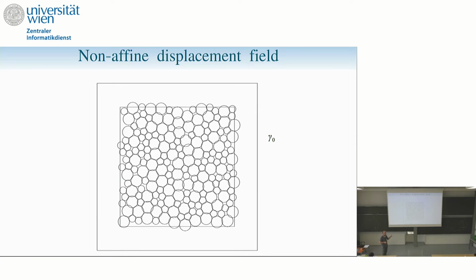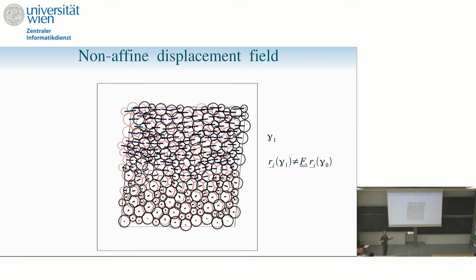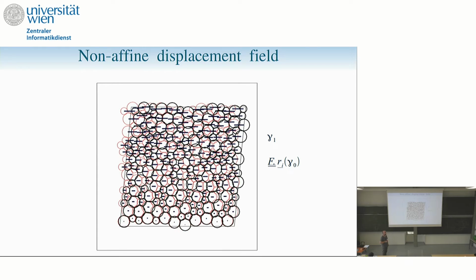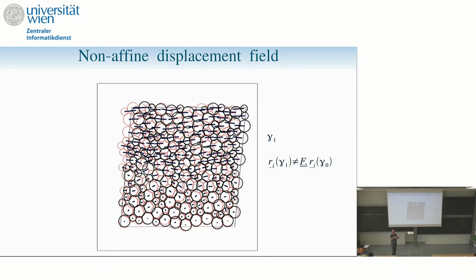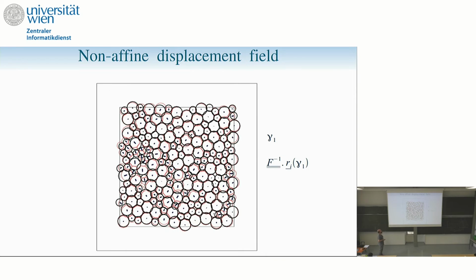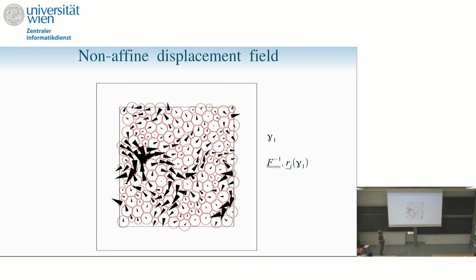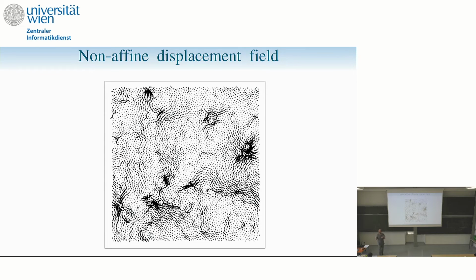Again, I start from a configuration. Here I shear affinely. I just bring the particles to the position specified by the macroscopic strain. That's it. There are periodic boundary conditions, yes. Now I minimize the energy. So I'm just decomposing the step I was showing you before: I strain affinely and then I minimize. Now I strain backward, and there is a residue. And this is a displacement field. If I take a larger system, I have this very large non-affine displacement.